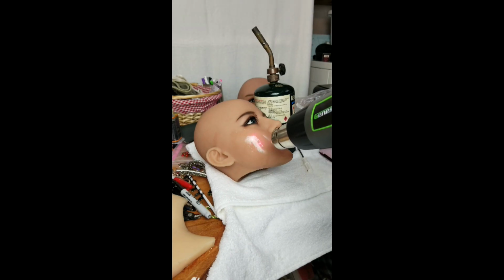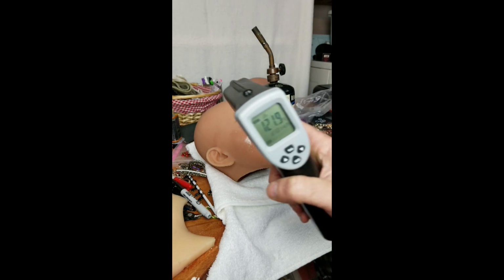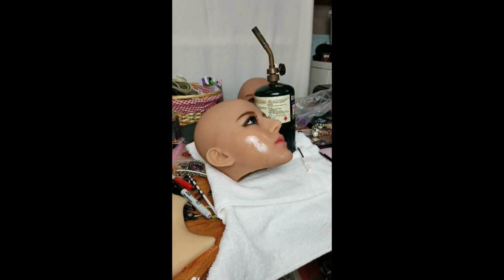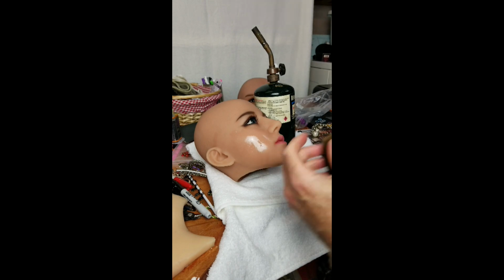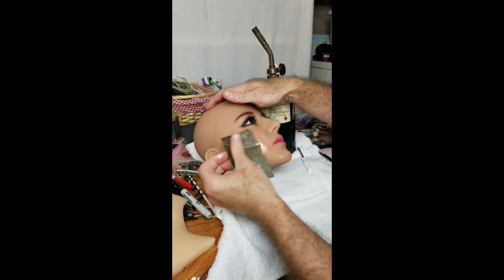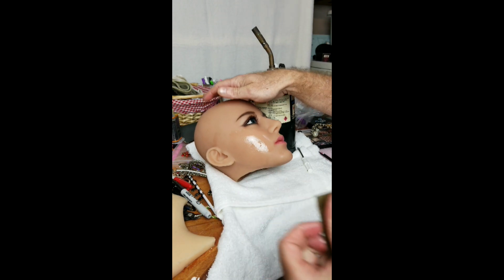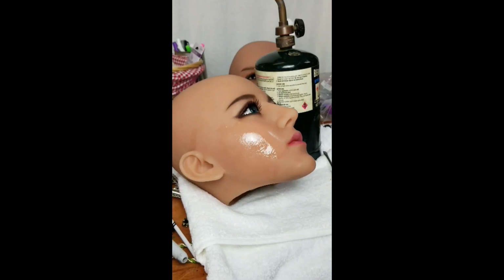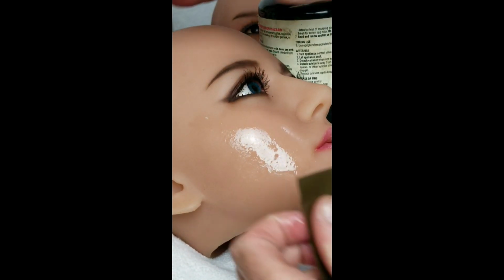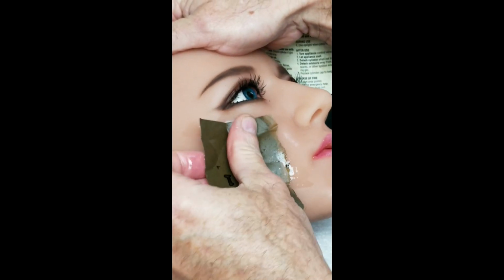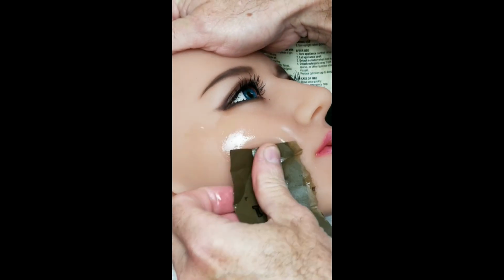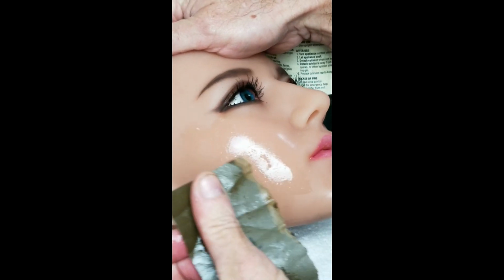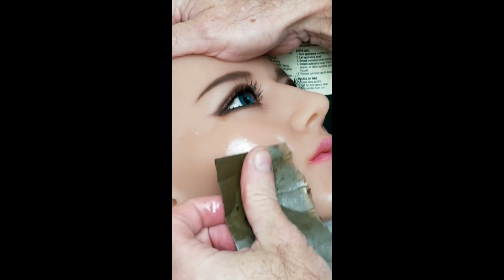This actual procedure will not work really well without oil, because the oil distributes the heat very evenly, and it's almost like a substrate for the melting procedure. So once we have the 120 C, you just tamp down with the wet sandpaper. So this is what they call a round of repair. So one round is one heating and one tamping with the sandpaper. And you'll have to do this for this repair probably 5 or 6 times.